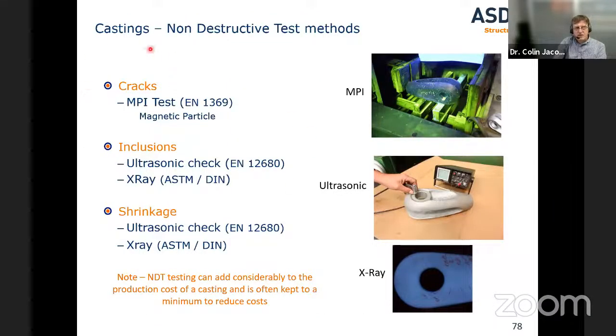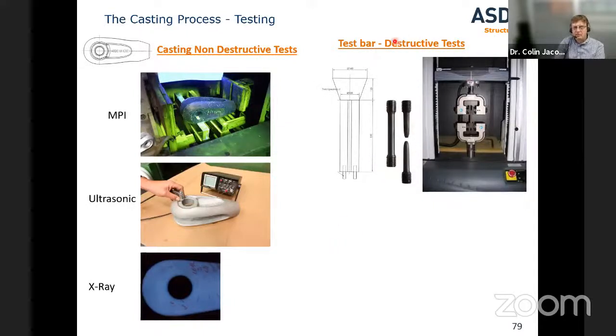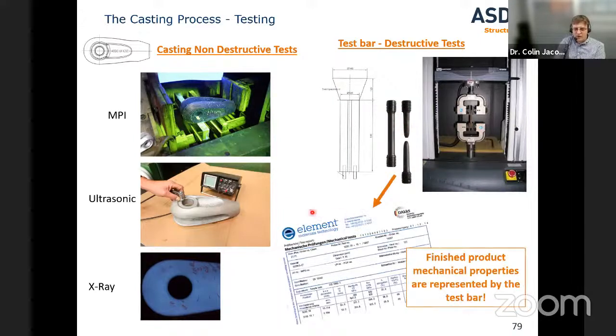For NDT, non-destructive test methods, you've got several methods. For cracks, you can use the MPI test. So we can test the product for cracks. We can test it for internal defects using ultrasonic, or we could even X-ray. Now, all these can be done without destroying the casting, but they do not tell us what the mechanical properties of that casting are. And to do that, we have to do a destructive test. So we have to take our test bar, produce tensile samples, test them. That will then give us our material test cert.